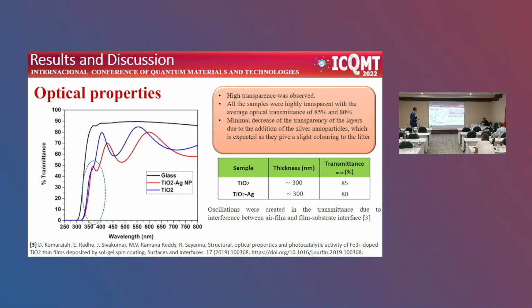Well, about these oscillations that are not normal in the titanium oxide: as you know, titanium oxide is totally white, so this type of absorption in the visible range is not normal. It is created in the transmittance by the interference between the air and the film, or the film and the substrate. It's not produced by the nanoparticles, and it's not produced by the titanium oxide. It's only an interference that a physicist could probably explain very well.